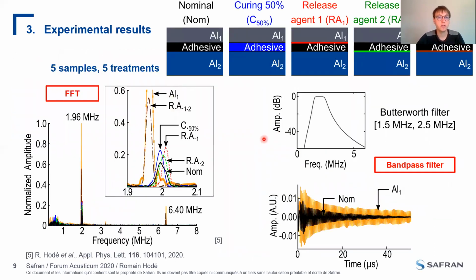And now, concerning the experimental results, on this 5 sample, we have obtained these frequencies. So in orange here, you can find the case of an aluminum plate of 1.5 millimeters, as I've shown you before. And the other curves are for the different measurements made on the different samples. What you can observe is that, for instance, for the nominal case, we don't have a clear resonance frequency, but it's more like we have two close resonance frequencies. But I will come back to this observation later.